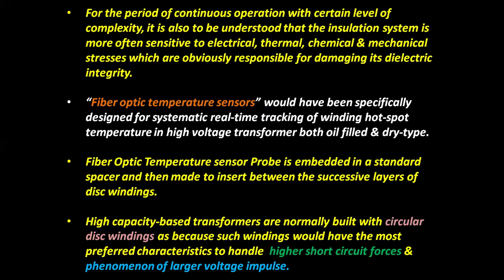Fiber optic temperature sensors are specifically designed for systematic real-time tracking of winding hotspot temperature in high voltage transformers, both oil filled and dry type. The fiber optic temperature sensor probe is embedded in a standard spacer and then inserted between the successive layers of disk windings. High capacity transformers are normally built with circular disk windings because such windings have the most preferred characteristics to handle higher short circuit forces and larger voltage impulses.